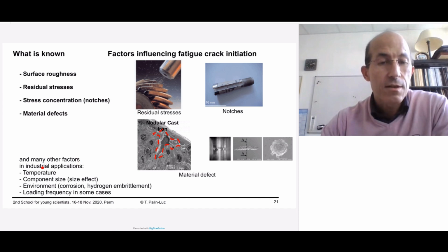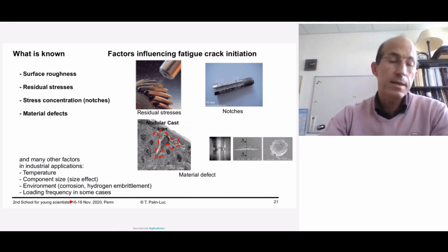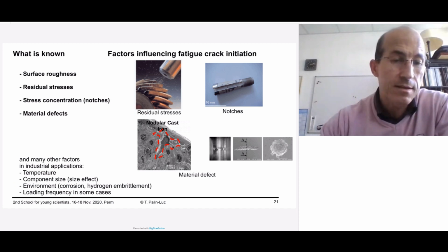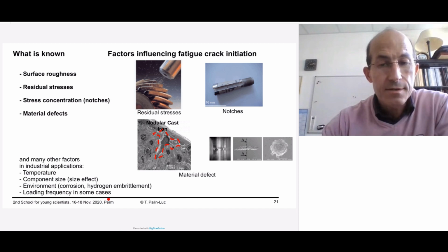For industrial applications, the temperature has an effect on the crack initiation. There is an effect also of the component size, because the larger the specimen or the component, the higher the probability to find defects. The environment plays a role also because of corrosion problems or corrosion aggression on the material, and also hydrogen embrittlement plays a role in crack initiation and propagation. And in some cases, for specific alloys, also the loading frequency, but this is less frequent. We consider that in metallic alloys, if the loading frequency is lower than approximately 200 or 250 Hertz, there is no effect.